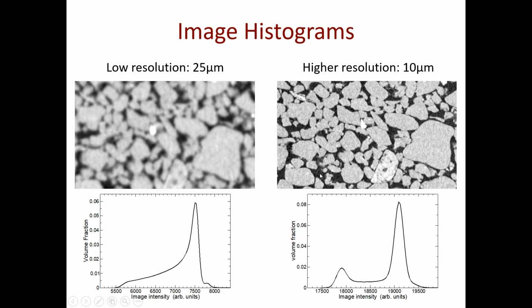And also, how much of a feature do I have? You can see that here, pore space, this is a sandstone, so this is 20% of the space, right? Versus 80% of the space. So I have no trouble seeing this peak no matter what, but this peak of 20% of the space could be swallowed simply because I have less of it. Of course it's also thinner in places. Yeah? And then this lower resolution swallows a lot of it. Yeah, overcomes. So histogram is often a quick look at whether I have a good quality separation.